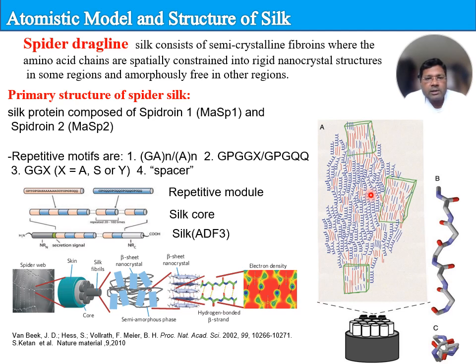The crystallites are irregular and strongly dependent on processing, for example the drawing speed, the rate at which the silk is extracted from the spider. Depending on the method, larger or smaller ordered domains can be identified as crystalline, shown here with the green boxes, along with side and top projections of a repetitive model peptide with dihedral angles to show the approximate threefold symmetry in the structure.